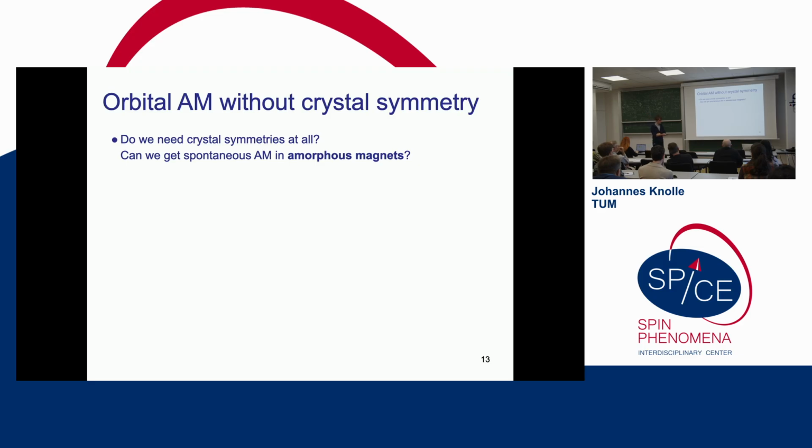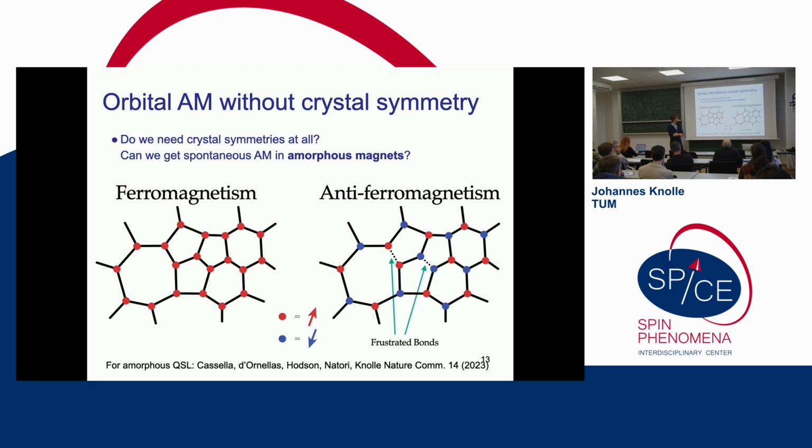And that is difficult. And the reason is that there are gazillions of amorphous magnets. You take your favorite magnet and you just grow it too quickly and it becomes amorphous. And usually, there are lots of systems which are ferromagnetic, but if you want antiferromagnetism, you realize that you can't get a bipartite structure in the system, so you usually end up with spin glasses, okay? But some of this wisdom that you also find in books does not necessarily need to be true, and we worked on some exotic spin liquid that can actually form in these amorphous systems.